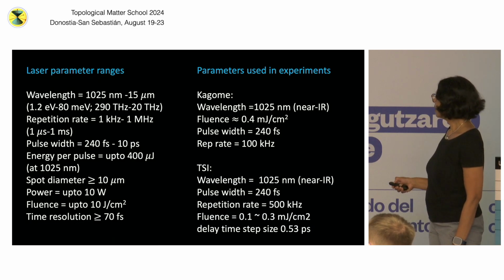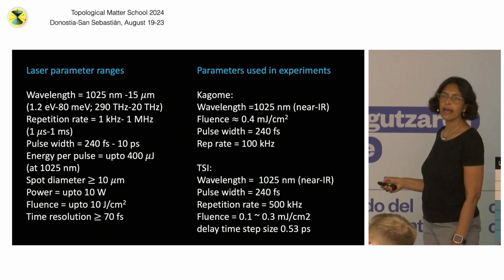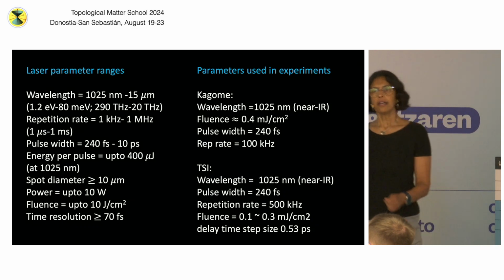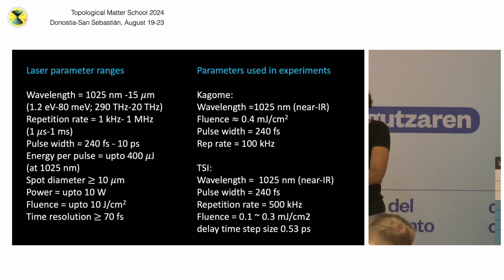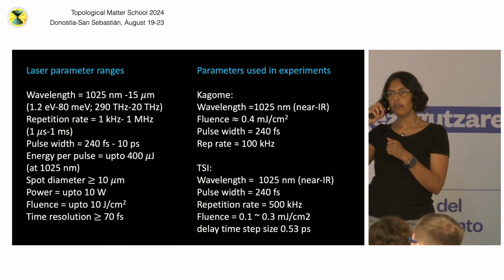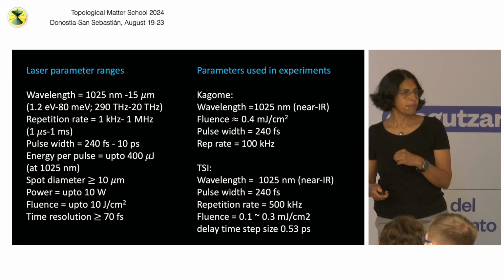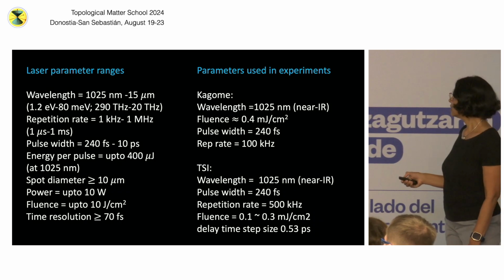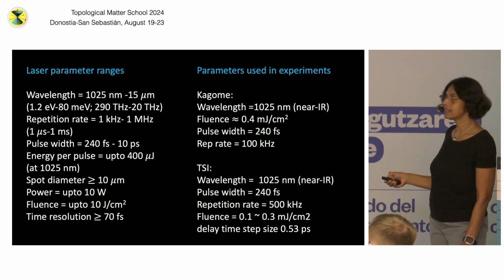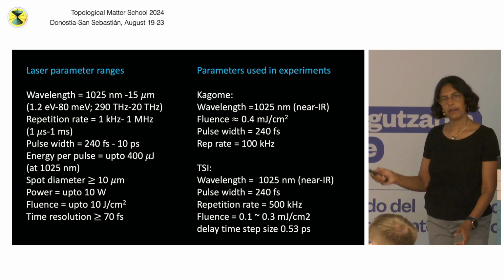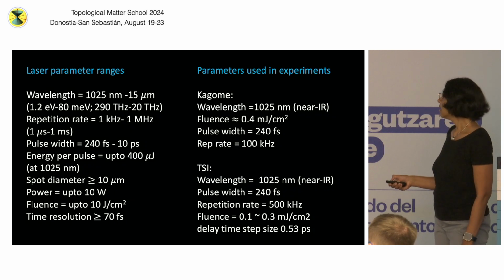There are a few important things here. The spot diameter. In order to achieve this tiny spot diameter of 10 microns, we had to install lenses inside our ultra-high vacuum chamber. These lenses are very close to the STM tip sample junction. It's a real physical lens, and that lens can be moved up and down, backwards and forwards to be able to focus the light onto the junction. So that's really important to get the fluence that we need. We have enough power to melt the sample and everything around it. Power is not a problem.